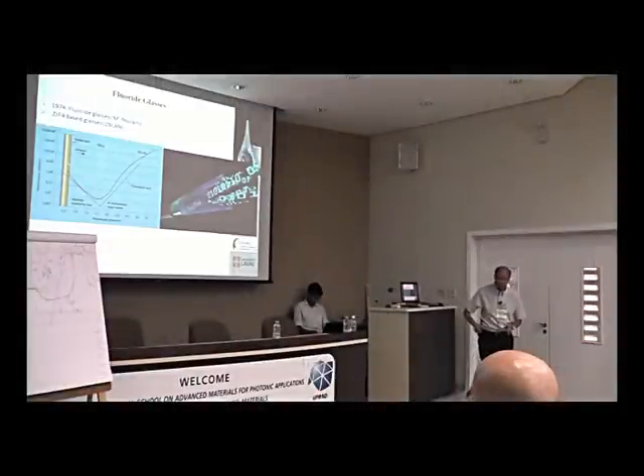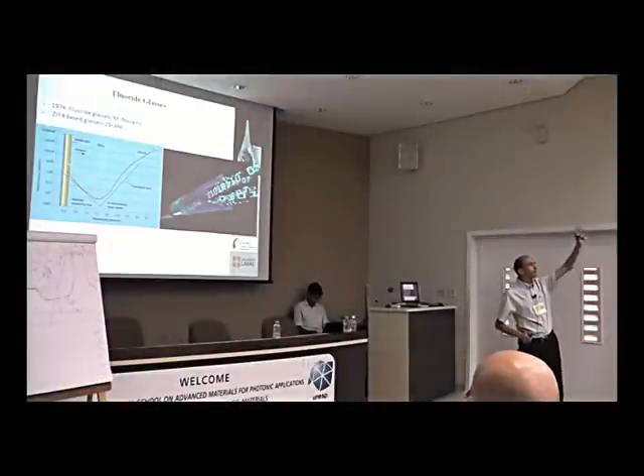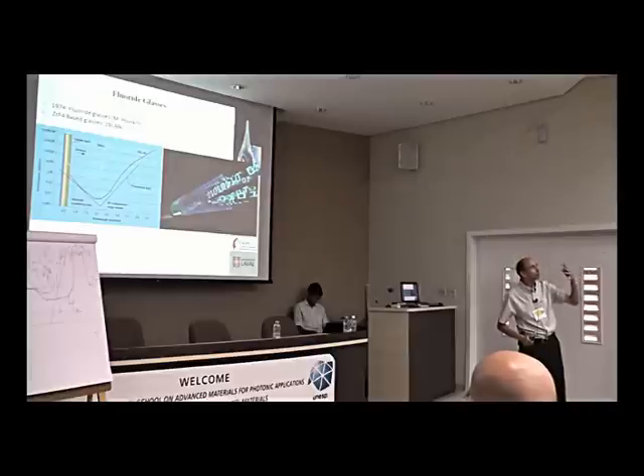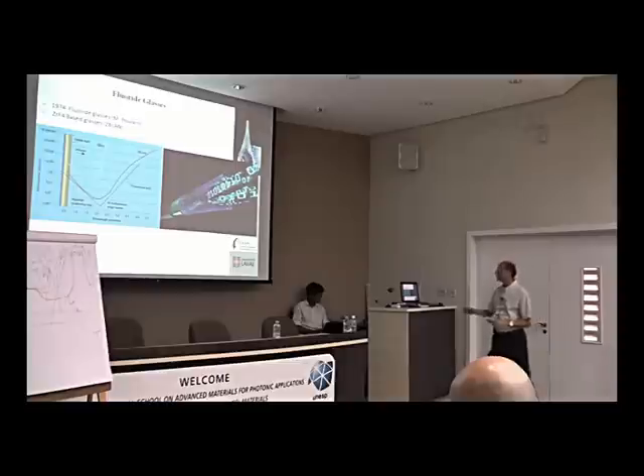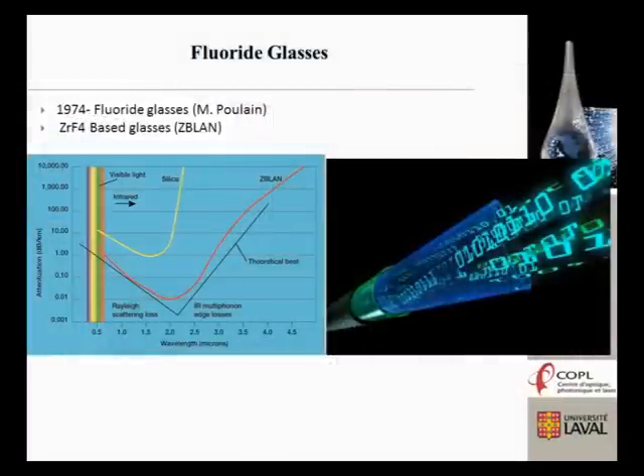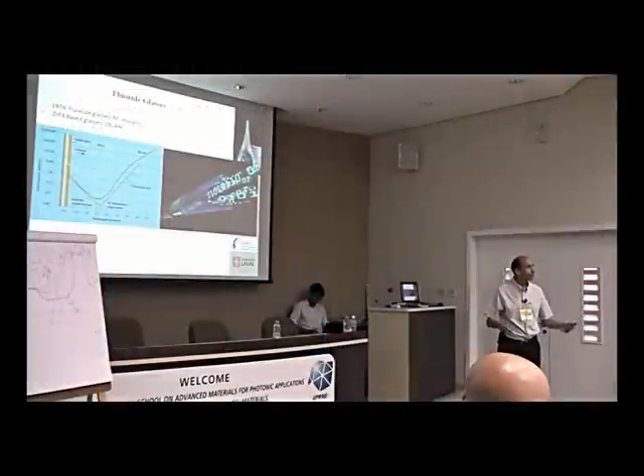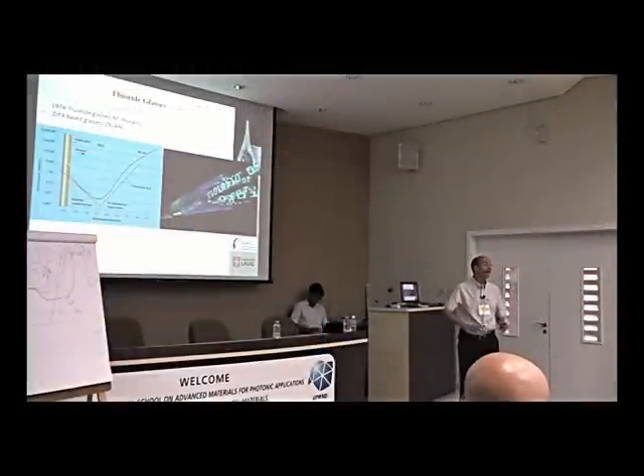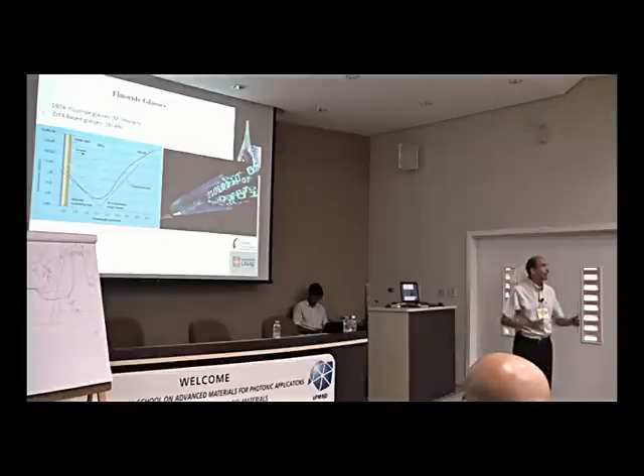Of course, in the chronology of development, I didn't put some changes during the years. In '74, Marcel Poulain in France, at the university, discovered a new kind of glass. This time based on zirconium, barium, lanthanum, aluminium, sodium fluoride. All these elements are fluorides. We're not discussing silica glass this time. This fluoride glass has a different behavior than silica glass. It has different viscosity, and again, different chemical bonding behaviors.